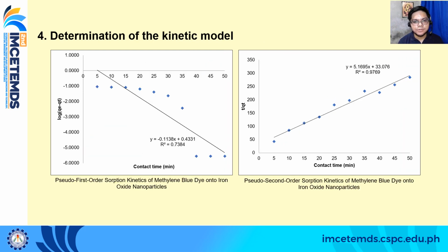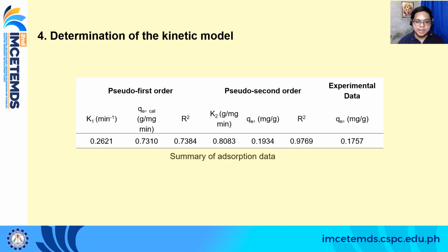And lastly, to better elucidate the reaction mechanisms and understand the adsorption diffusion form, we used three kinetic models, namely pseudo first order, pseudo second order, and simple Elovich models, to also determine the rate controlling step for the entire reaction during the adsorption experiment. Here is the summary of the values for all the models that we used. The correlation coefficient, or R squared, for the pseudo first order kinetic model was relatively low, and the calculated qe value was 0.7310, or 0.73, which does not agree with our experimental data, which is 0.1757.